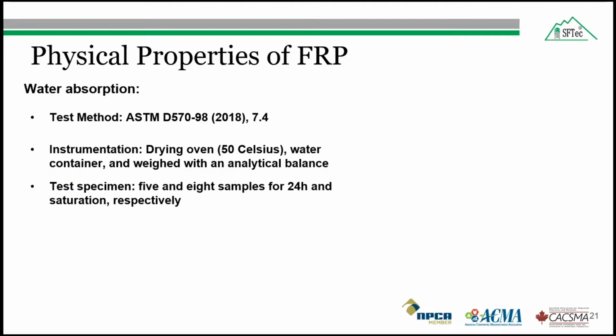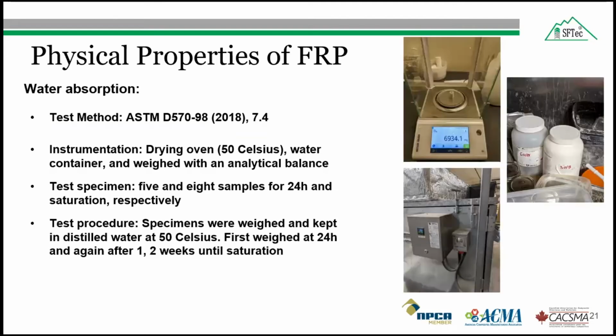So a total of, for each production lot, 5 and 8 samples for water absorption for 24 hours and saturation respectively were tested. So the specimen were initially dried in an oven for 24 hours and weighed after cooling in a desiccator, and it was called the condition weight. So I will tell you what is the condition weight later. So after conditioning, the specimen were placed in the distilled water kept at 50 degrees Celsius in this chamber. So we place the bars inside this and put it in this chamber, which were regulated at 50 degrees Celsius. Then the first weighing occurred after 24 hours, and then the specimen were immersed in water again, extracted and weighed every alternative weeks until saturation.